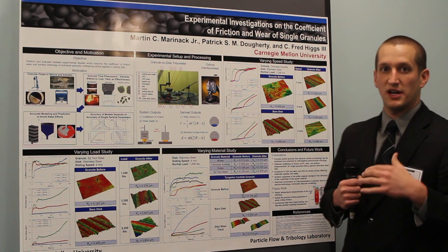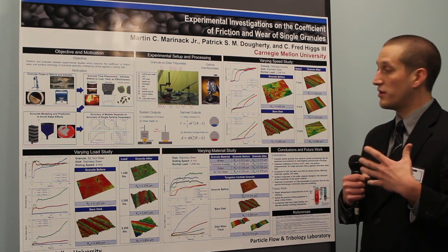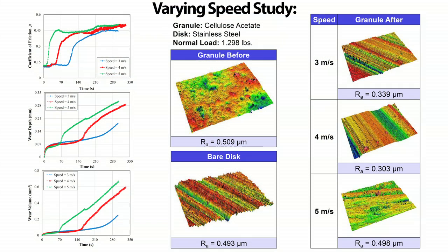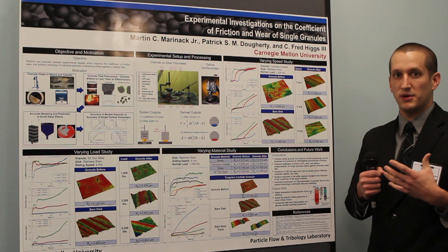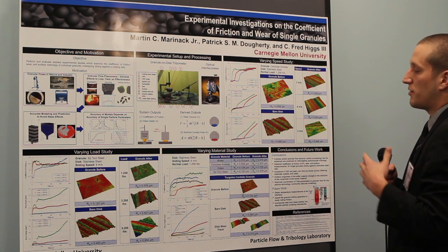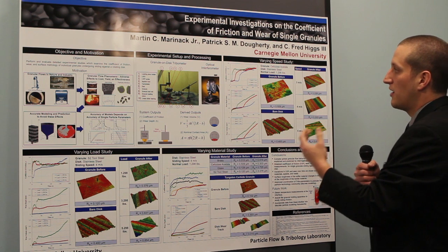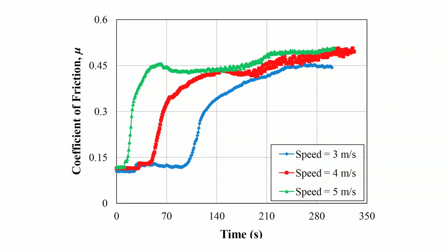So we did several different studies on several different materials. One of those studies was looking at varying speed. And so the material we study here is a cellulose acetate material. This is the material that is commonly used in granular flow validation experiments. And so one of the most interesting results we see here is that when we look at coefficient of friction in particular, we see that over time the values of the three different sliding speeds approach a similar steady state value. But what happens is they get there at different rates.